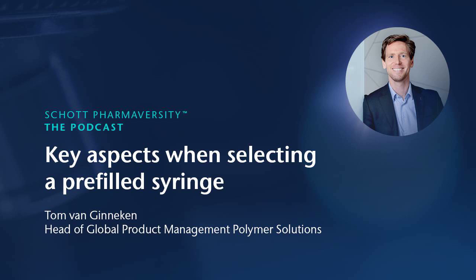Again, this material is not perfect. Even here, there are some drawbacks. First one, it's still a polymer, and polymers tend to be semi-permeable from a material perspective. So barrier properties are definitely not as good as glass. This can be relevant, obviously, for oxygen-sensitive molecules. There, glass might be the preferred option. Also, the polymer material is not suitable for all kinds of drugs, for instance oily substances. These oily substances can react with the COC material of the syringe and can degrade the material.